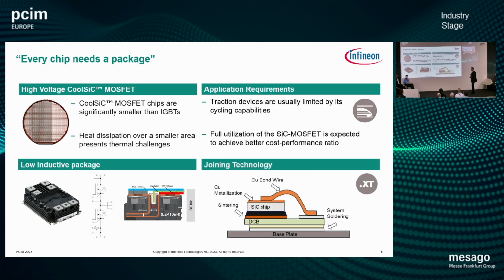What it brings, of course, in combination is that we not only rely on just the chip, but also introduce the .XT technology. With .XT, what you clearly see is that the silicon carbide chip is sintered to the substrate, and on top we have the copper metallization and the copper bond wire. The clear advantage it brings is a very high power cycling capability.